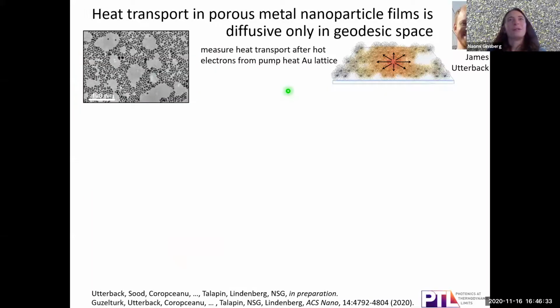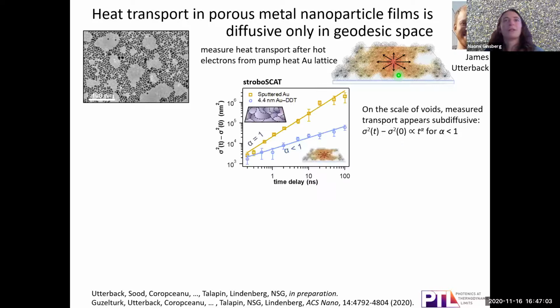Okay, so before I do that, I want to give you one example, just looking at thermal transport on its own in films of a few nanometer gold nanoparticles. When photoexcited hot electrons give energy back to the gold lattice, you can think of this as basically instantaneously happening on the timescales of heat transport that we're interested to measure in this film. So stroboscat uniquely enabled James to see subdiffusive heat transport. In other words, the mean squared expansion is scaling sublinearly with time, as opposed to what you would see in, say, pure gold. And so what causes this non-diffusive behavior?